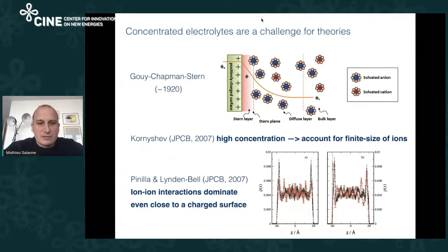For example, there is a large body of work made by Alexei Kornyshev from Imperial College in order to account for the higher concentration in more complex theories. Also, 2007, more or less when I started to work on this project, as was said by Leonardo, is the moment when other people started to work on ionic liquids at interfaces. And this is an interesting work by Ruth Lynden-Bell in Cambridge. She showed that even if you charge your surface, you don't end up separating the ions easily. And the reason is because they like each other a lot. So cations like to stay in the vicinity of anions and vice versa. And so it's very difficult to understand the structure because you have these strong correlations.